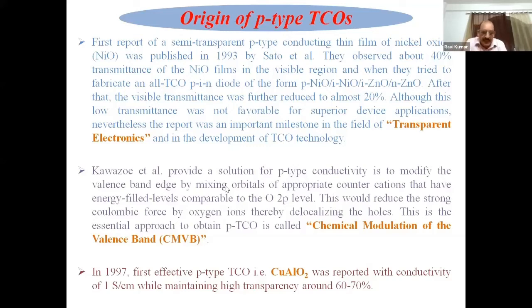Then we go by the literature. The first p-type TCO material was copper aluminium oxide, reported in 1997, which can maintain a transparency of 60 to 70%, and the conductivity is again very poor, 1 Siemens per centimeter.